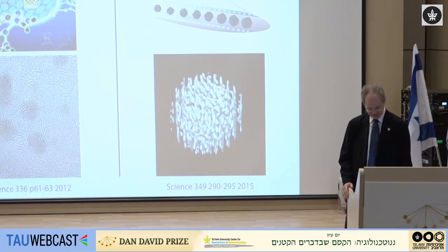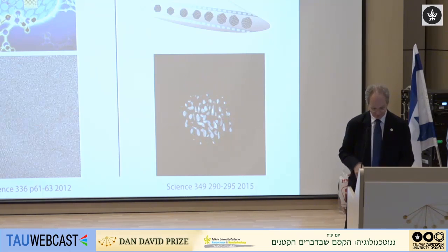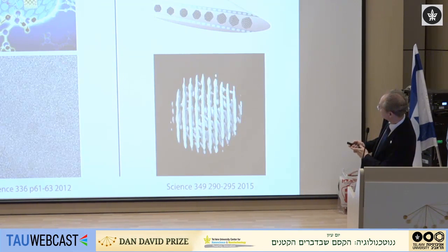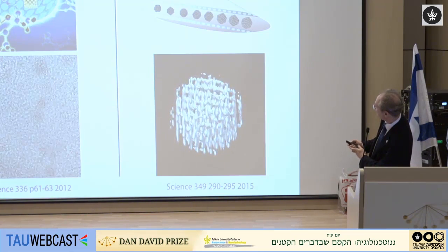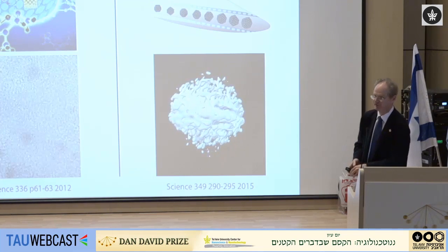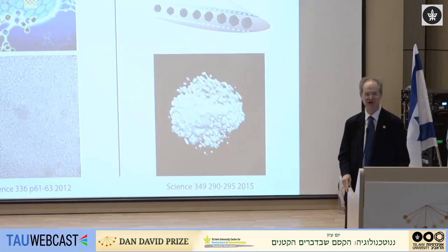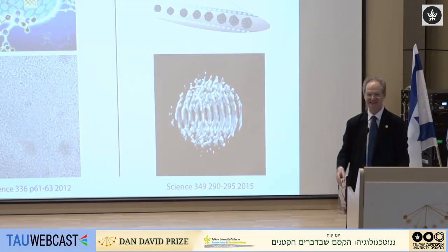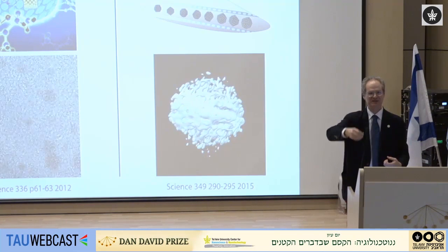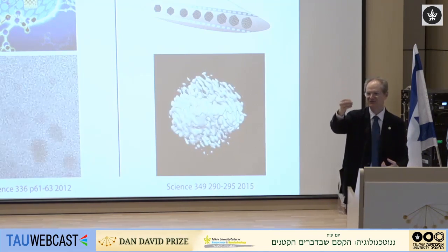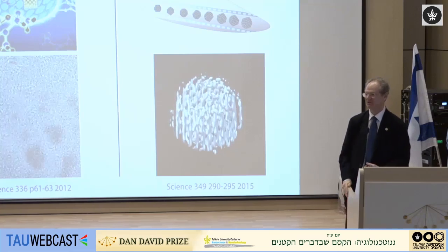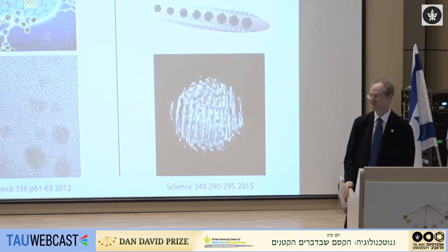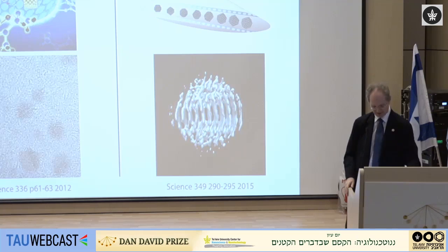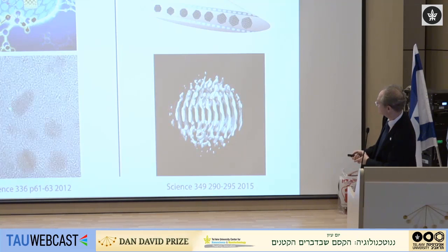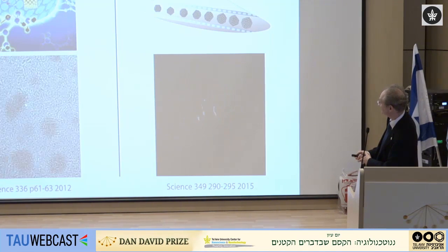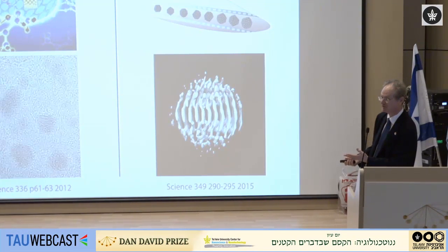we grow particles inside a liquid cell, and over time we've developed that into a special kind of liquid cell where the liquid is trapped between two layers of graphene, so that the window is a single layer of carbon. The consequence is that the electron beam is not scattered too much by the window. Of course, it is scattered a lot by the liquid, which creates a lot of background noise and makes it noisy. But you can see here an example in this movie of some platinum nanocrystals. We're taking very heavy atoms now in order to observe them easily.